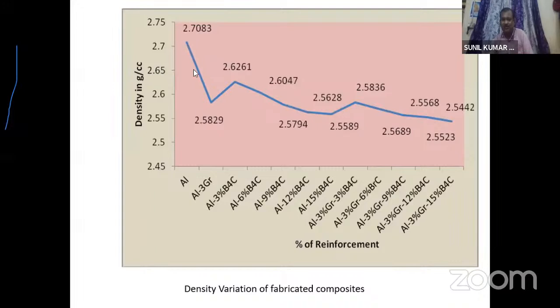So this is pure aluminum. Once graphite is added, the density suddenly decreases. Why? Because graphite is a less dense material. Then if you are adding B4C, there is an increase in the density. Then as you go on increasing the B4C content, the density of the composites decreases. So this is related to only metal matrix composite. These values are related to hybrid metal matrix composite. Here we are going to use graphite also. Hence, some increase is there, and thereby a decrease.